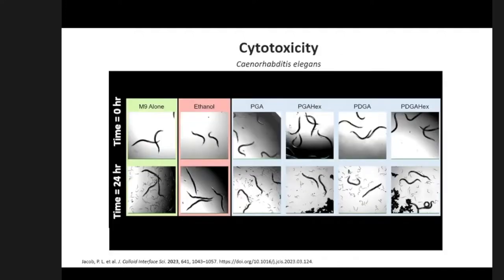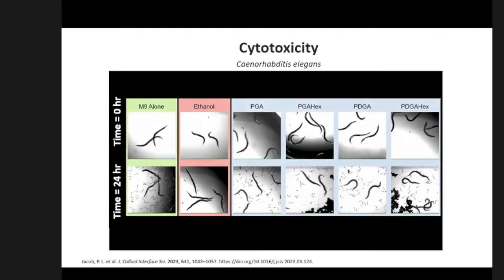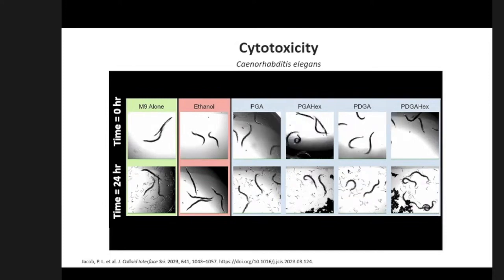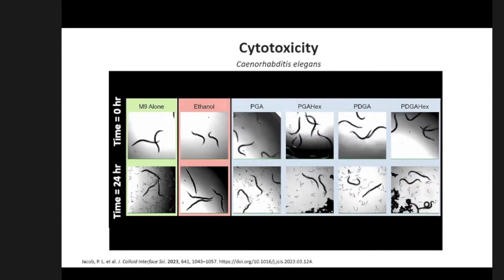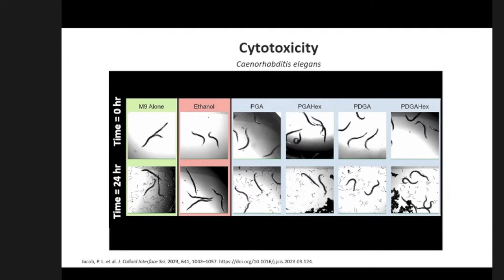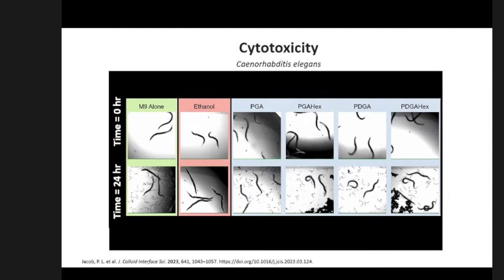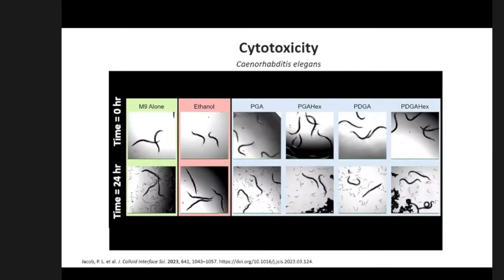Moreover, cytotoxicity was evaluated both in vitro and in vivo on Caenorhabditis elegans, worms belonging to the nematode phylum. And as you can see from the video, after 24 hours, nanoparticles did not show any toxic effect compared to the blank, therefore corroborating their biocompatibility in vivo.